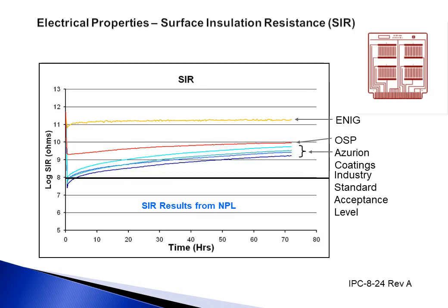I then decided to have the surface insulation resistance measured, because given the low resistivity that I'd encountered in the Z-axis, I was concerned that there might be low resistivity also in the X and Y plane. So I went to NPL and got them to carry out a series of SIR tests, and you can see the results here. Our coating is not as good as ENIG, not even as good as OSP, but still above the minimum industry standard acceptance level.